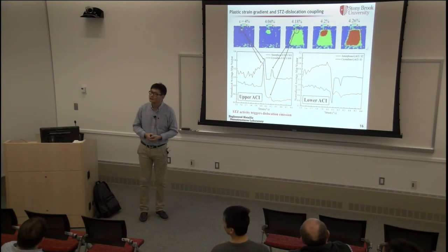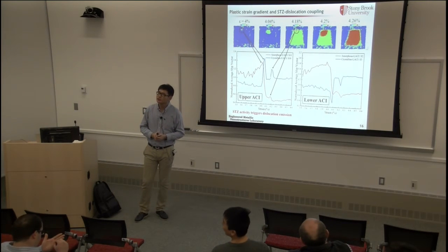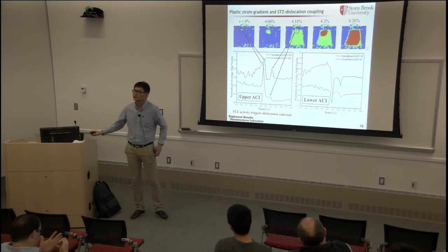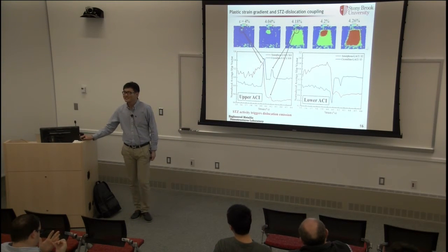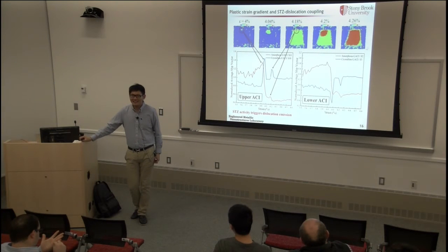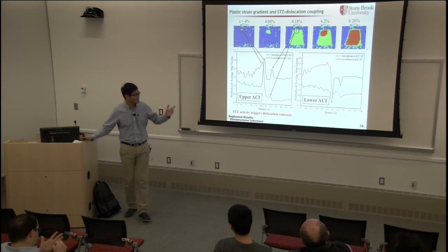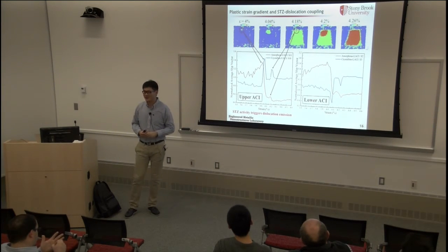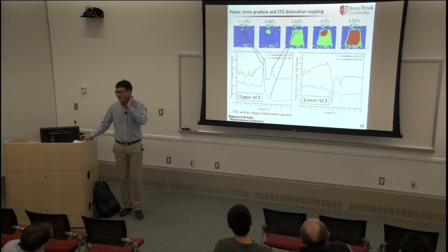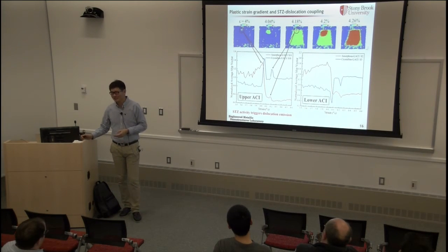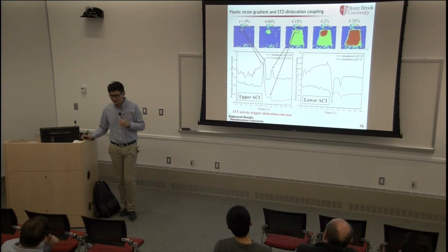So you did a lot of these studies using LAMMPS. Can you talk a bit about the calculations? How much computer time? Did you use MIT? Yeah. So my structure is a 10 nanometer structure. It's about 2 million atoms. I use a strain rate of 10 to the 8 per second, which is actually a slow strain rate in computational work. Normally this is what I use.